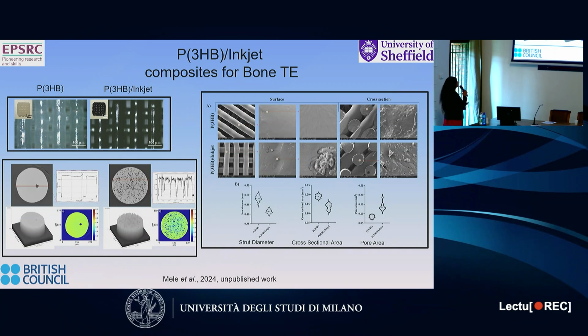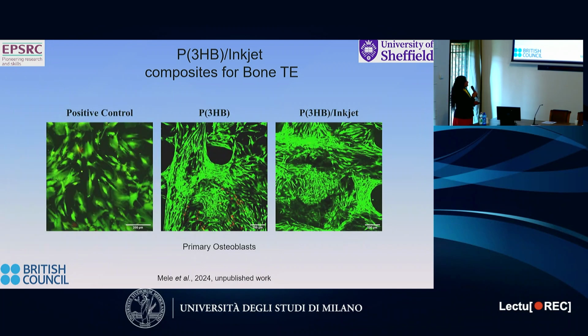So here we are. We've printed these composites with inkjet. You can see here how nicely porous the composites with inkjet are versus the neat polymer. And the struts were much more well-defined when we added inkjet, and we got a lower diameter, a lower cross-sectional area, and a higher pore area. All very positive. So the inkjet proved to be an excellent filler, and here we are, primary osteoblasts growing wonderfully on these composites. You can see not only are they growing on the polymer struts, but also trying to jump across them. So it's really a wonderful environment for these cells.